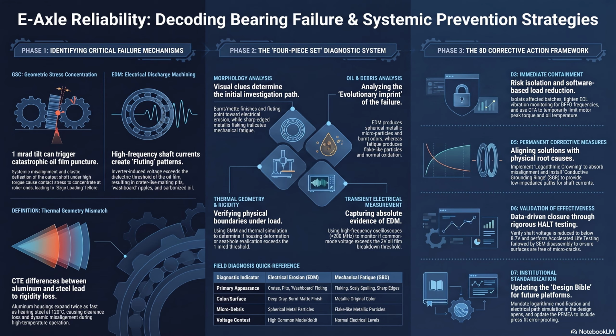Right. When that 1 milliradian tilt happens, the contact stress at the edge skyrockets. The document notes it exceeds 2.5 gigapascals. Okay, 2.5 gigapascals. Let's put that into perspective for a second. It's a lot. Atmospheric pressure, the air pushing down on us right now, is about 100 kilopascals. The pressure at the very bottom of the Mariana Trench is roughly 100 megapascals. Right. 2.5 gigapascals is 25 times the crushing pressure at the bottom of the ocean, focused onto a sliver of steel the width of a human hair. It's an astronomical amount of force.